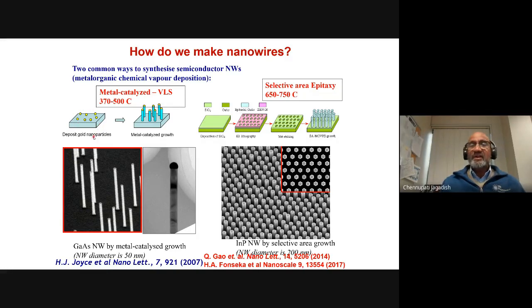So then if you put this on a gallium arsenide substrate, for example, put this in an MOCVD reactor, heat it up to somewhere between 370 to 500 degrees Celsius, then you're creating this gold gallium eutectic liquid, and you introduce the gases needed for the growth of gallium arsenide, for example, trimethyl gallium and the arsine. These gases get incorporated into this liquid alloy, it gets supersaturated, and then they get precipitating out. And you always see the gold nanoparticles on the top, and the gallium arsenide is precipitating out of this nanoparticle.